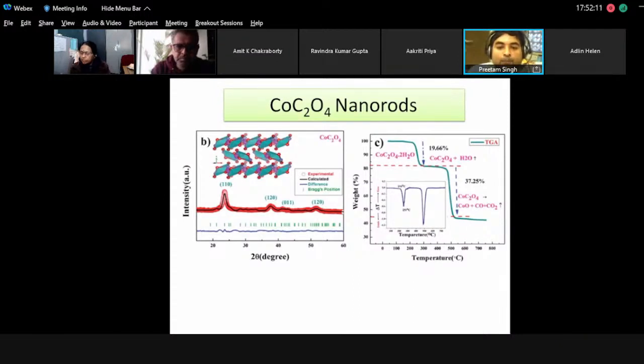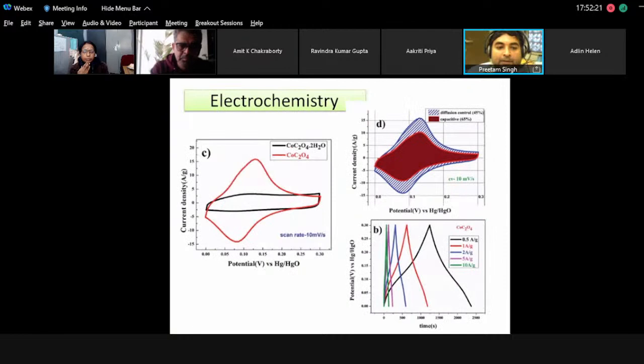But if you do a controlled heating profile, which we have done, with low temperature water removal, we have converted them into nanorod type structures, and they have performed. If you see the black line of the hydrated cobalt oxalate compared to the anhydrated cobalt oxalate, there is an enormous increase in the capacity, and now you are seeing the clear intercalative behavior of this Co3+/Co2+ redox couple, which is very, very active now.